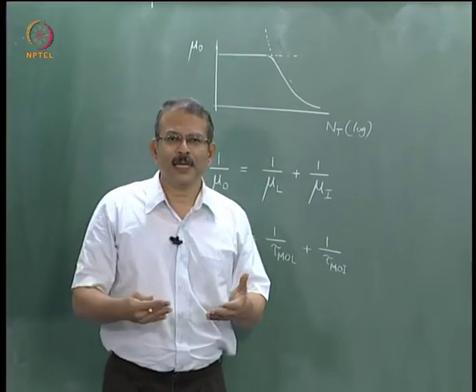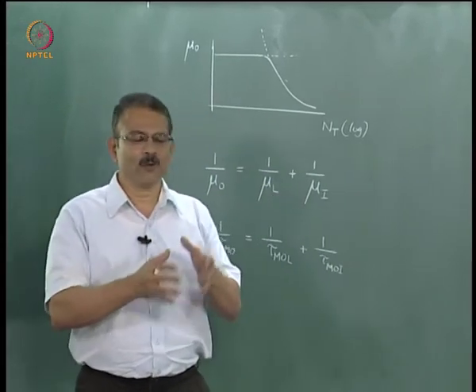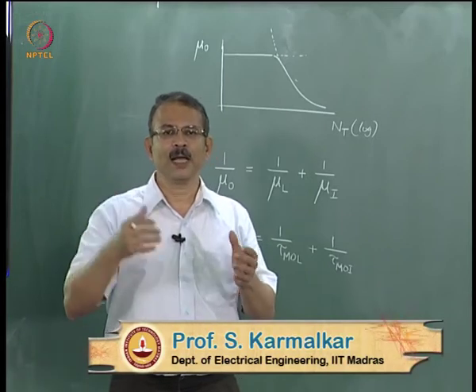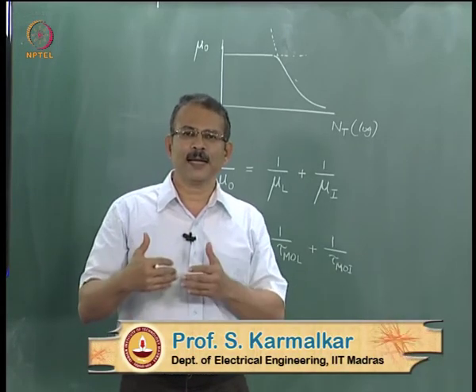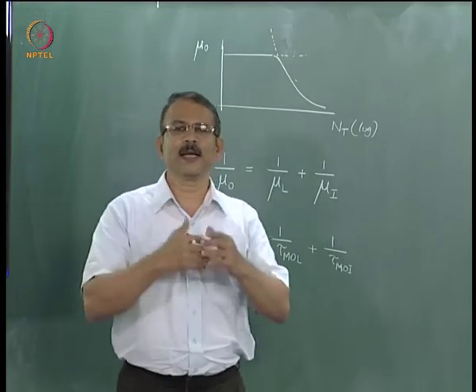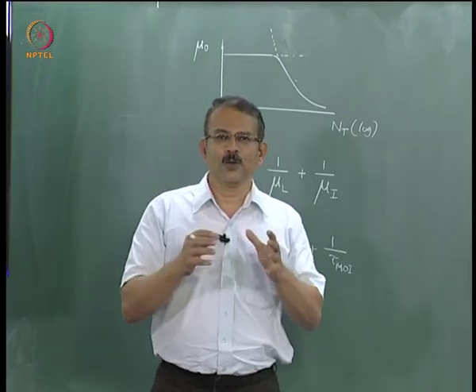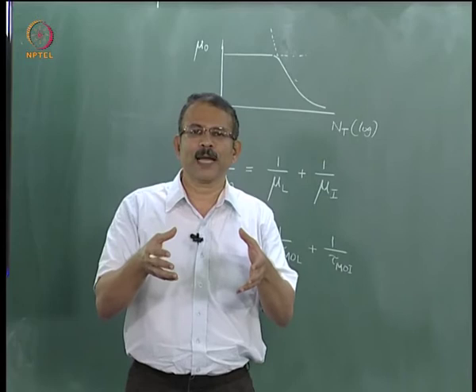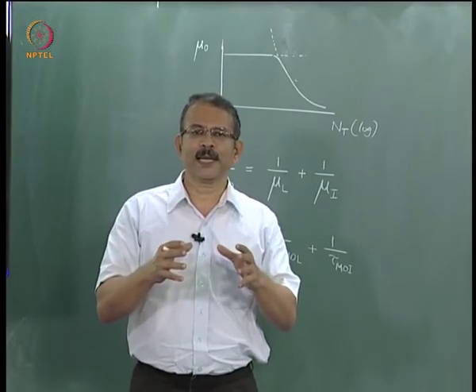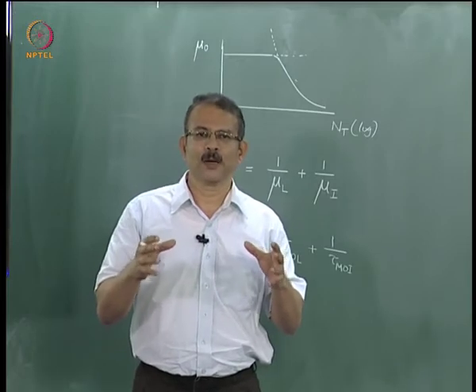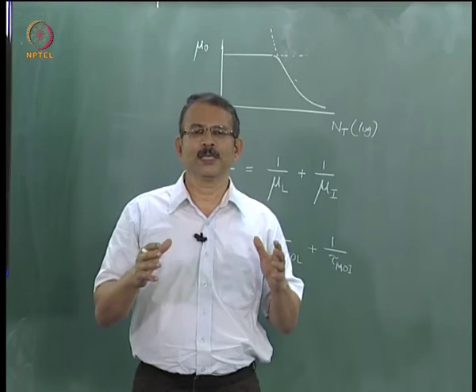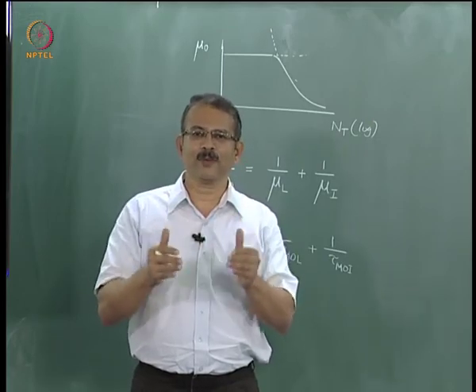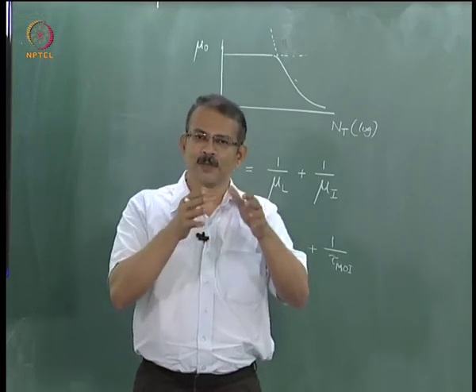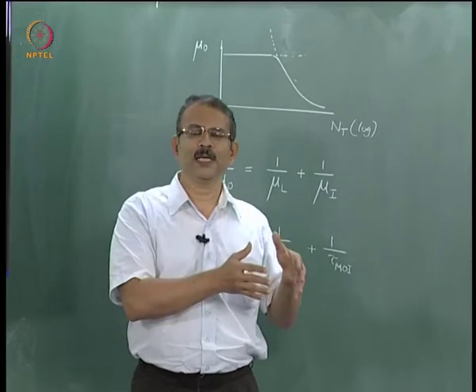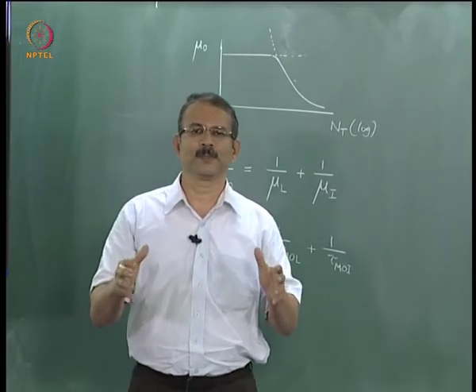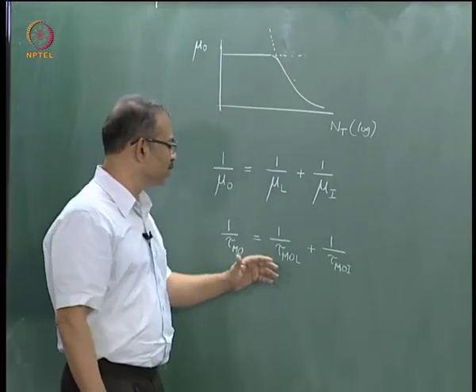Now intuitively it is very easy for you to recognize that if I have one mechanism of scattering, I get a certain scattering rate. Then if I add another scattering mechanism, the scattering rate of this mechanism would add on to the scattering rate that was already there. Now you can ask, but how can you just superpose two scattering mechanisms and their rates? Yes, strictly speaking it may or may not hold in practice. Okay. So however, we make an approximation that the scattering rate of a number of scattering mechanisms is the same as the scattering rate of each mechanism considered individually, and then their rates are all summed up. Okay. So this is an approximation that we are doing. This is also referred to as Matthiessen's rule.